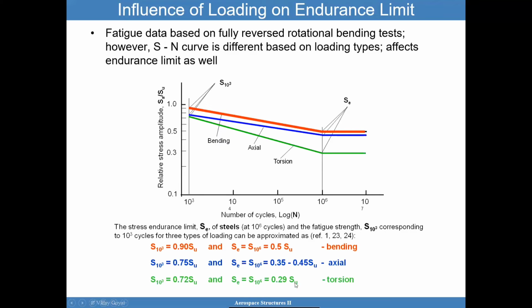So if you go to steels, I had said 0.5, but that's for bending. When I have torsion now, I can drop to 0.29. It's important to get this right because a lot of people will make mistakes here. Another consideration is that the strength at about 1,000 cycles will be about 90% of the ultimate for bending, 75% for axial, and then 72% for torsion. So it's very important to understand that the loading condition can affect the situation at hand.